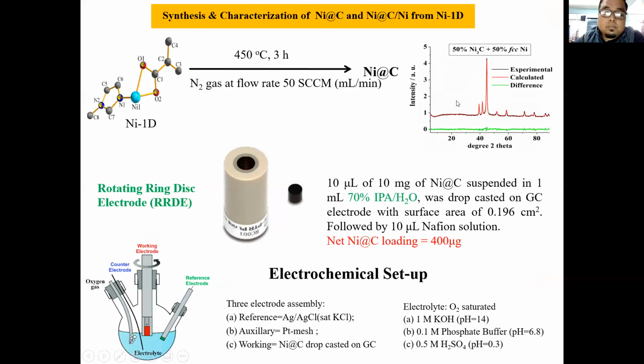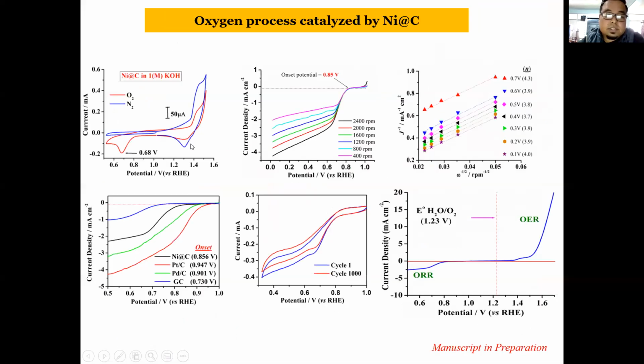Now this composite is modified into an electrode. We coated this material over a glassy carbon electrode, and we formed an electrode of this nickel composite material and did some electrochemical reactions. The electrochemical reactions that we chose were specifically the oxygen reduction reaction and the oxygen evolution reaction. We know that in fuel cells, both these oxygen reaction processes are very important.